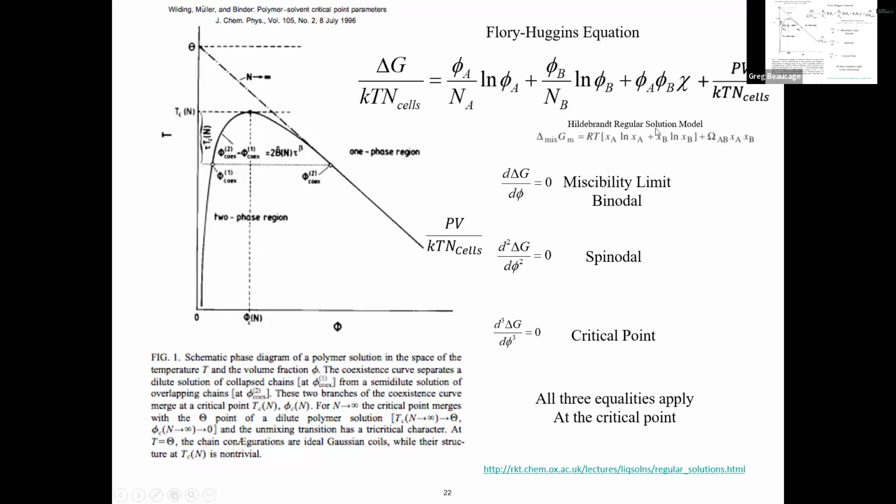They're kind of the same equation. It's something you should be familiar with, but probably didn't remember or didn't care, but anyway, that's the Flory-Huggins equation. So if you put in NB is 1 and NA is a polymer, so it's got 100,000 molecular weight, then this term is larger than that term. And also you lose symmetry. You can't just swap A and B anymore because the two terms are different. So then you get this skewed shape, it shifts the curve.